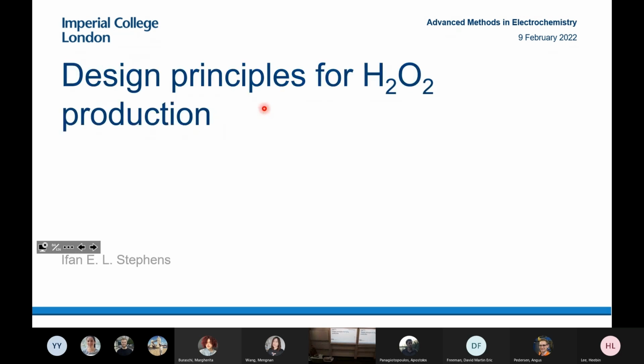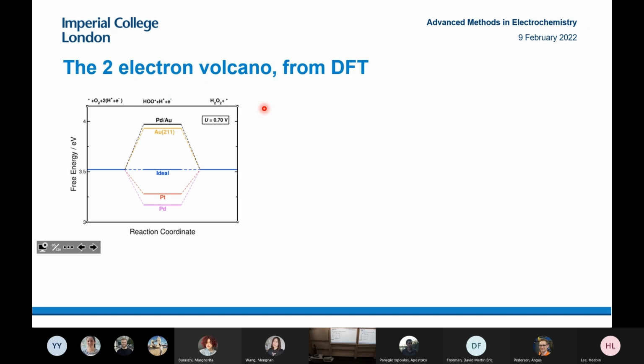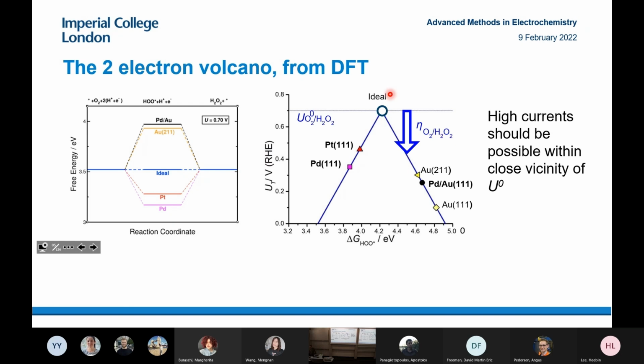Then Samir Sharastami and Jan Rosmas did some more DFT calculations, trying to understand the reaction on already known catalysts. This is a free energy diagram for hydrogen peroxide production from oxygen at the equilibrium potential. The ideal catalyst has a completely flat free energy profile, as shown before, for 4 electron reduction. They could see that already known catalysts like gold or palladium-gold are quite uphill to form the OOH intermediate, explaining why the activity isn't that good. The ideal catalyst will have moderate binding to OOH, and the already known catalysts are not in this region. But if you could get this ideal catalyst, you should be able to get high currents in close vicinity of the equilibrium potential.